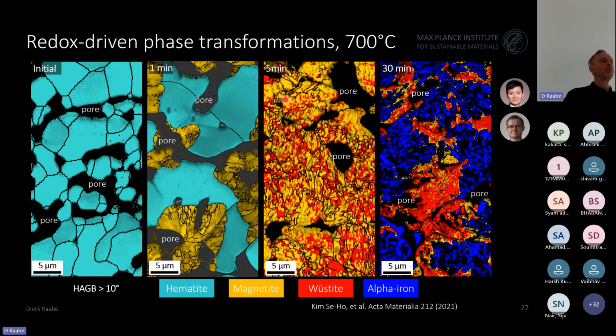Now, when we go towards 5 minutes, we see the decomposition of the hematite into magnetite and wüstite, as you see here. That is a very, very interesting phase transformation, as I will also show on the next slide, because it's not a classical nucleation growth process, but it looks like a reshuffling of the iron cations in that lattice, which is, as I said before, for magnetite and wüstite, the same when it comes to the O2- positions. So that's a very interesting type of phase transformation. And remember, that's that part of the transformation where things also get very, very slow. And then you arrive finally, of course, at the formation of the alpha iron at 700.